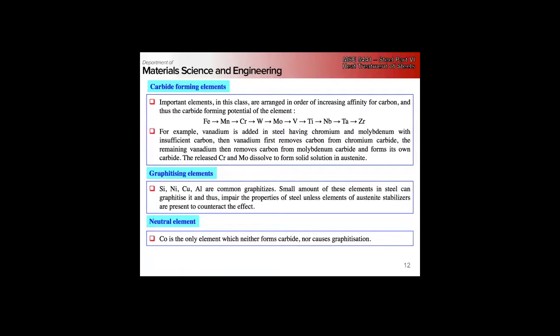These carbides basically give us strengthening in the same way that the secondary phases in aluminum do. So playing with the alloying elements not only allows us to mess with the austenite and ferrite phase fields, but also to play with the structure of these carbides to give us additional strengthening, much like we would have in aluminum.